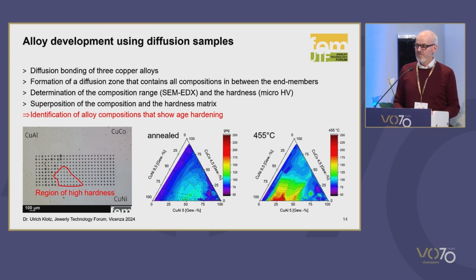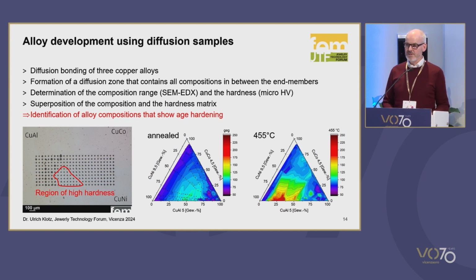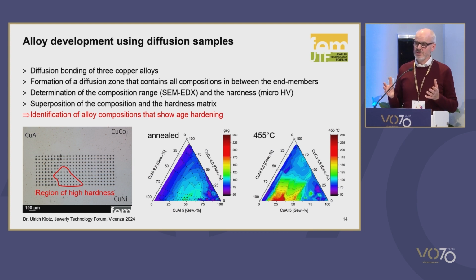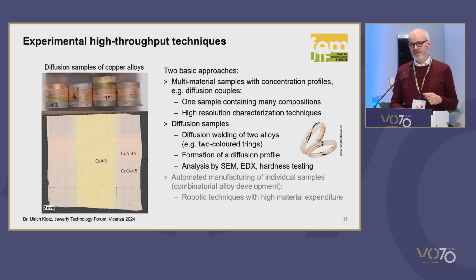And this diagram was measured on the same sample, but after the sample has been annealed at 450 degrees for some hours. And then the so-called age-hardening process is taking place. And we see that there are compositions that show high hardness, while others still are staying soft. So with this method, we can screen a whole composition range and find alloys that have the potential for age-hardening. With all these samples that are shown here, we have thousands of compositions that we can screen with a few samples.